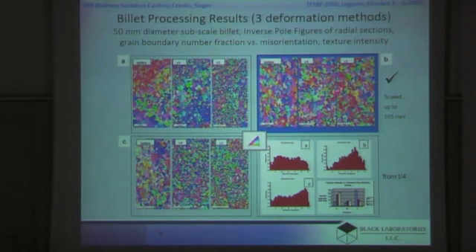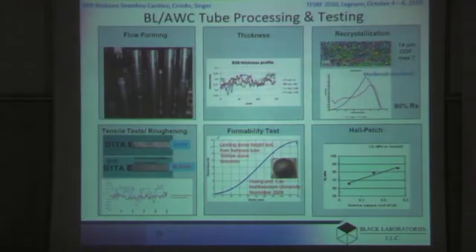Another indication here that this was the most useful, and this is something we rely on a lot to project the stability of the fine-grained structure, and that is that the grain boundary angles showed a nice distribution. Instead of going more towards the low angle boundary side here, the boundaries here in this section were peaked towards the high angle and showed quite close to random distribution. We also looked at the crystallographic texture intensity, and process B here had from the outside, the middle, and halfway between had the most uniform intensity of texture. When we produced the tube,